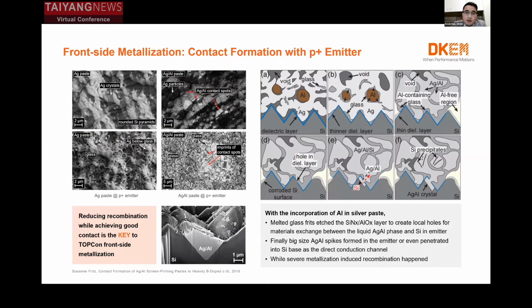The right picture shows the mechanism of how the silver aluminum spikes form. Actually, with the incorporation of aluminum in silver paste, the melted glass frits will etch the silicon nitride and aluminum oxide stack layer to create local holes for material exchange between the liquid silver aluminum phase and the silicon in the emitter. Finally, big size silver aluminum spikes will form in the emitter, and some of them will even penetrate into the silicon base. This kind of big size silver aluminum spike will take a role as direct conduction channels.